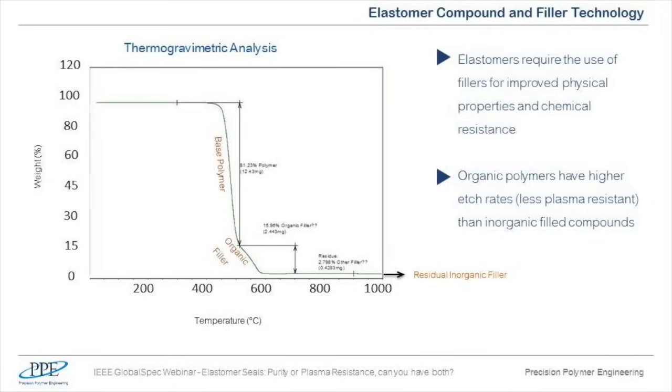So in this specific example, you see the weight loss has started at around 450 degrees, which corresponds to the decomposition of a main polymer in the formulation.